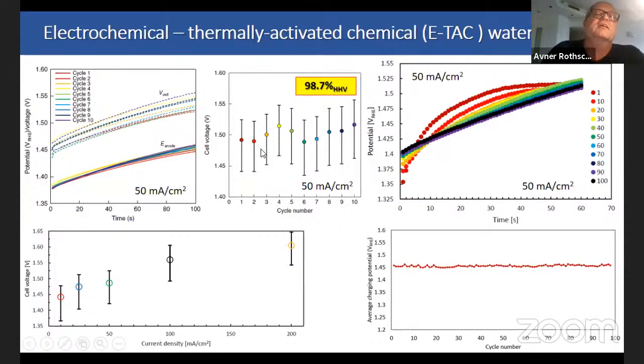So specifically, we operate the cell at current density of 50 milliamps per centimeter square at an average voltage of 1.5 volt. Obviously, the voltage and the anode potential changes during the reaction because the state of charge changes, okay? But the average is very low, 1.5 volt compared to a state-of-the-art electrolyzer that operates at 1.8 volt. So we can save more than 20% in the energy. This reaction is highly cyclable.